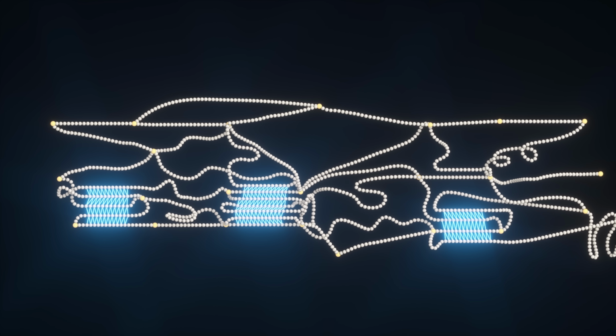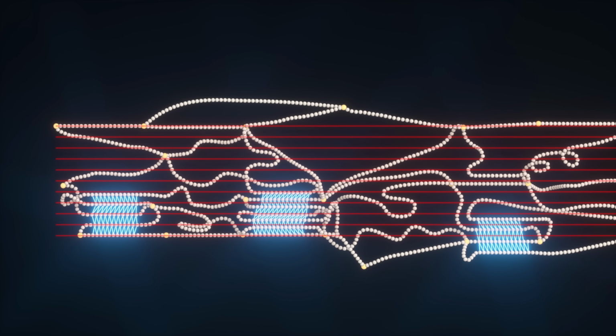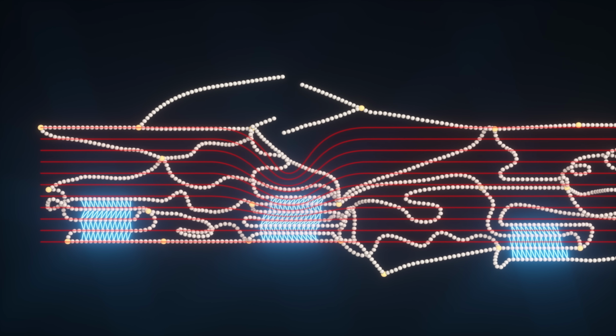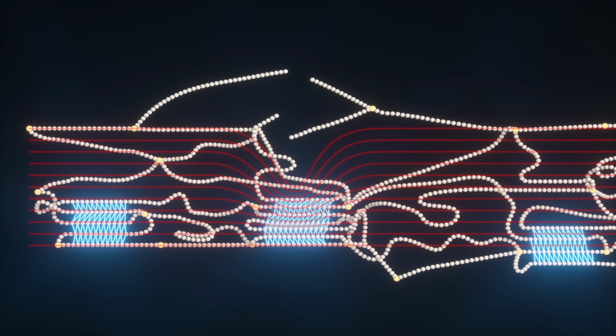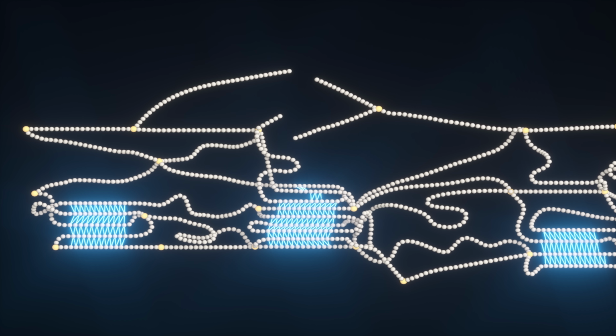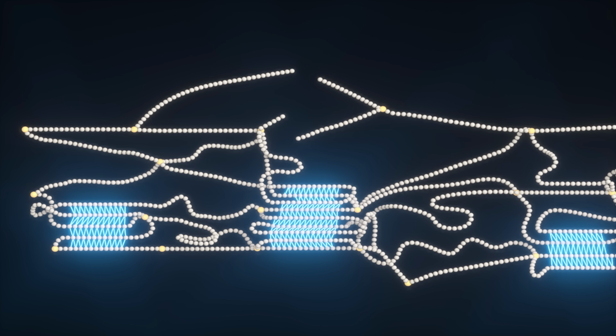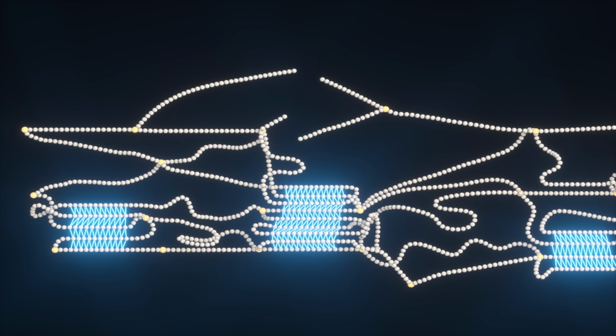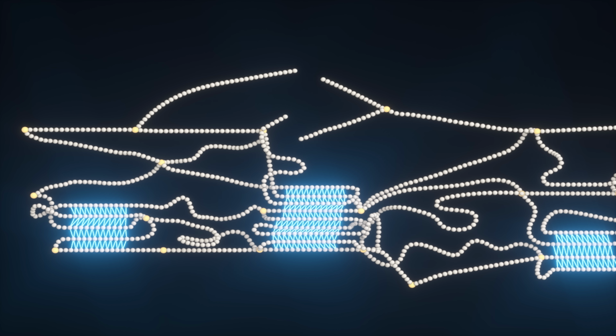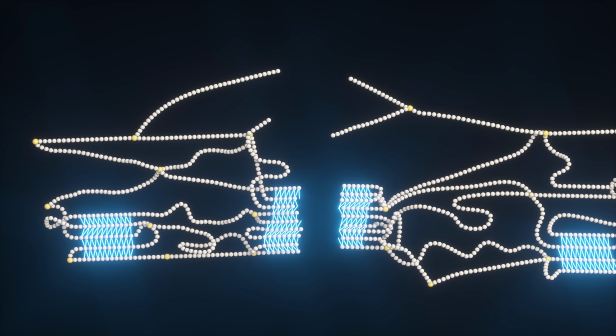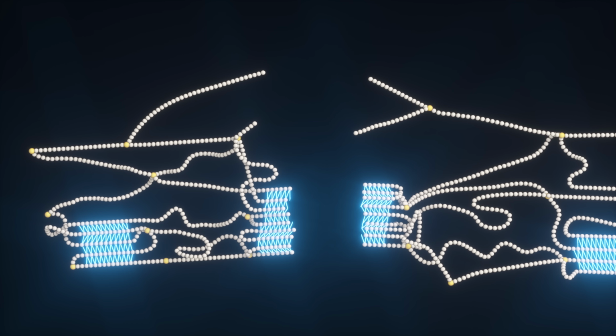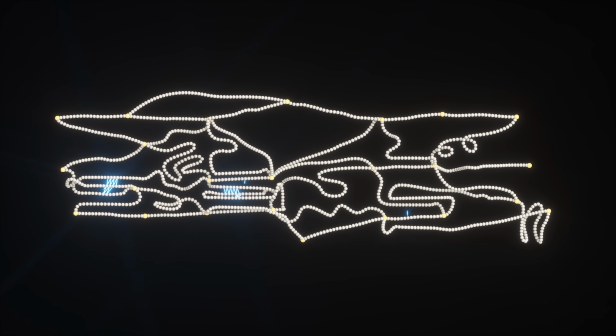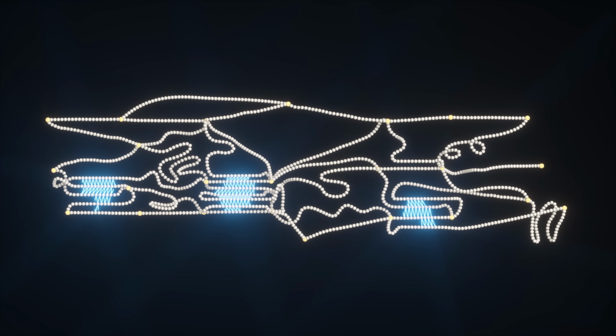That ability to form crystallites prevents tear. So if you have crack propagation, it hits a crystal and can't go any further. In a sample without a crack, the stress is evenly distributed. But if there is a crack, more load flows right to the edge, so the rubber stretches more. That area forms more crystals, so it becomes harder to break. The crystals stop the crack growth until a threshold is reached, and then it breaks. This is what makes natural rubber so durable. It's self-reinforcing under stress, stopping cracks in their tracks.